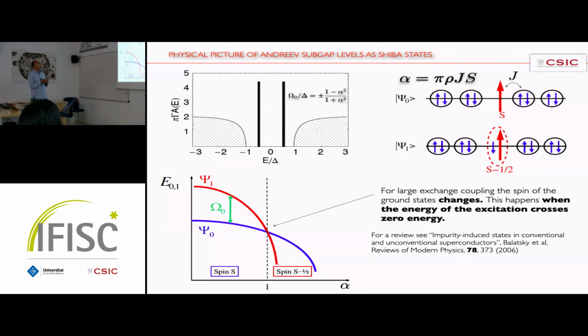So you can have two possible configurations: the essentially free spin, or weakly coupled spin to the superconductor, or, if the exchange is large enough, you can actually bind singlets. You can break Cooper pairs and bind singlets between the impurity and the now free spins coming from Cooper pairs. And these are actually the Yu-Shiba-Rusinov singlets. The energy you gain in this process gives rise to these resonances inside the gap of the superconductor. And the position in energy of this resonance is given, at this classical level, by this expression in terms of alpha.